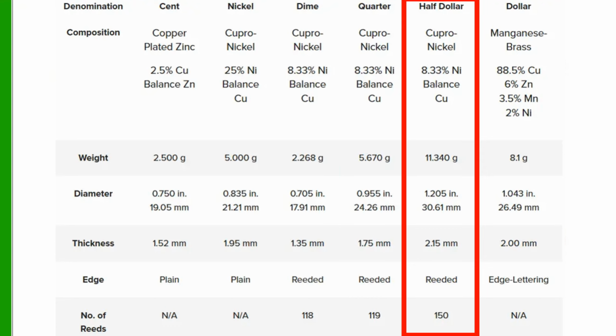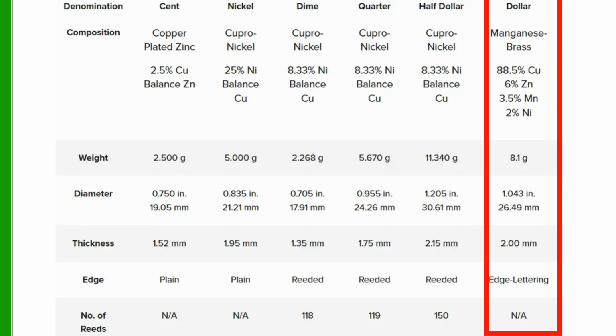The half dollar continues with the 8.33% nickel copper composition. It is the heaviest of the cupronickel coins, weighing in at 11.34 grams. It also has the largest diameter at 30.61 millimeters, with a thickness of 2.15 millimeters. Now, it also contains a reeded edge, and the half has 150 reeds on this particular coin. The dollar, on the other hand, is a unique composition. This one, as they affectionately call the gold dollar, isn't gold at all. It's what they call a manganese brass. It consists of 88.5% copper, 6% zinc, 3.5% manganese, and 2% nickel. It weighs 8.1 grams and has a diameter of 26.49 millimeters. Now, the thickness on this one is exactly 2 millimeters.